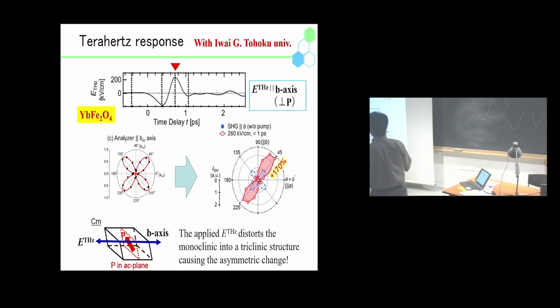Why did we observe such asymmetric angle dependence in the lutetium Fe2O4 or ytterbium Fe2O4? This is the unit cell of this material. We apply the electric field along this direction, the b-axis. If we apply a strong electric field to the system, the crystal symmetry changes from the original monoclinic structure to the triclinic structure. So by applying the electric field, we observed triclinically distorted systems. That is the reason why we observed such an asymmetric shape of the azimuth angle dependence.